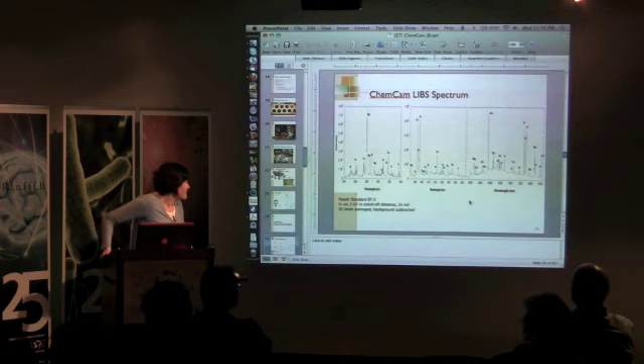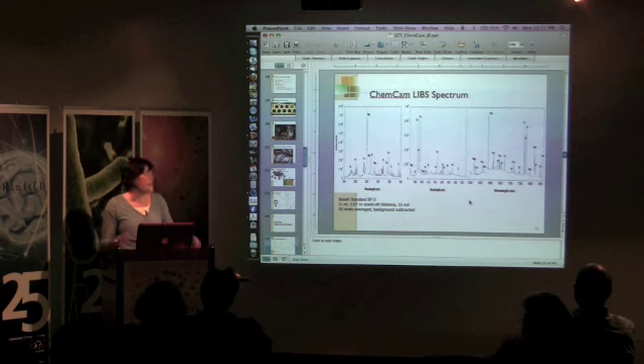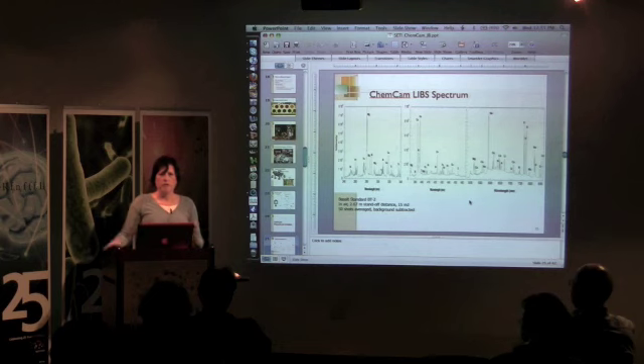I noticed in that spectrum that you have up right now, it looks like there's a nitrogen peak around 750. Is that due to nitrogen in the solid target, or is that from the atmosphere near the target? In this case, it's most likely from the air. Is that because your laser is actually ionizing the air, or is it the heat from the target plume that's doing that? I assume the air is being ionized from the plasma stream, but we don't know for certain. I just wasn't sure if your laser was powerful enough to ionize the air directly. We used a power for this spectrum of 50 millijoules, and ChemCam will be using somewhere between 15 and 17 millijoules. That's extremely low power, an order of magnitude lower than laboratory measurements. Okay.